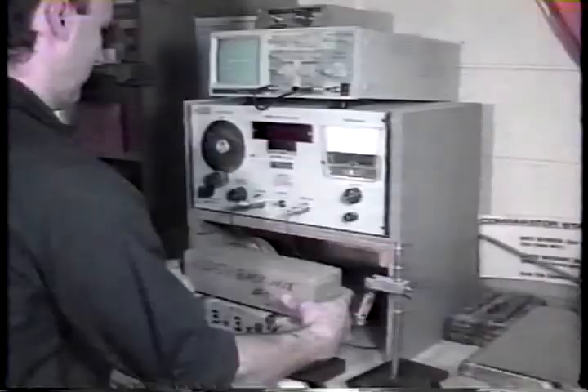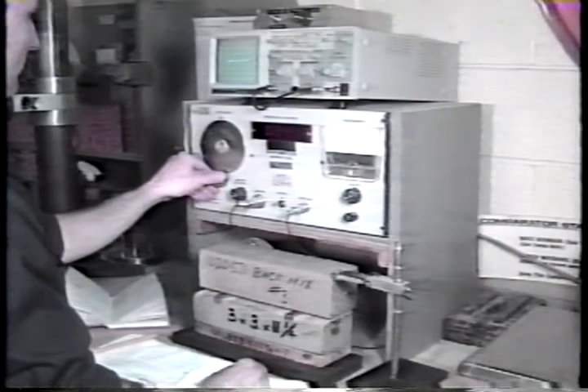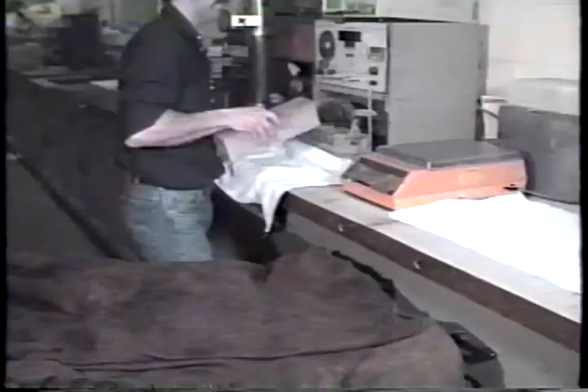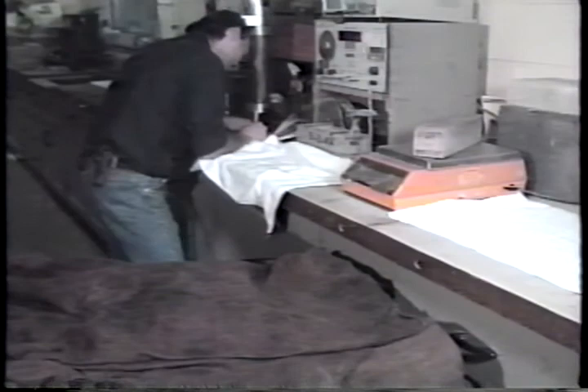Then they're tested for resonant frequency using the equipment described in ASTM C215. The resonant frequency is related to the stiffness of the specimen — if damage occurs during the freeze-thaw test, the stiffness will decrease, reflected by a decrease in resonant frequency. At this point, you should also weigh the test specimens to the nearest gram. Generally, but not always, damage from freezing and thawing will remove part of the surface layer of concrete and be reflected by a loss of weight.